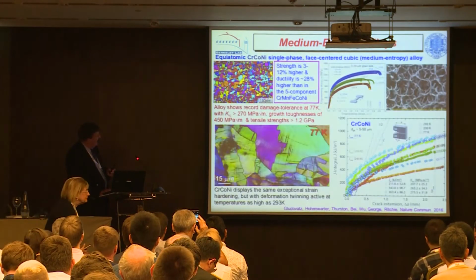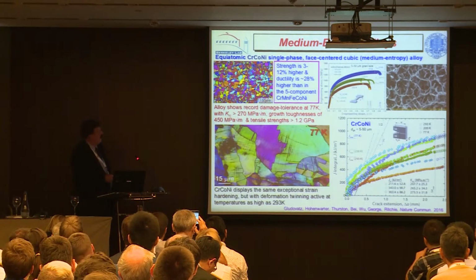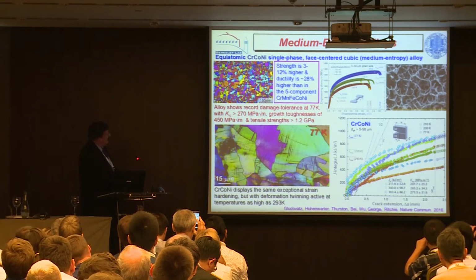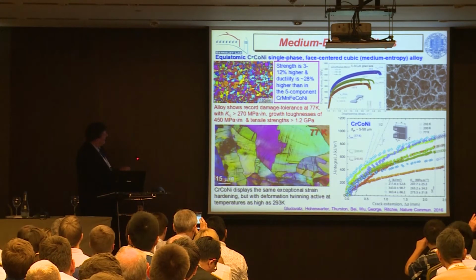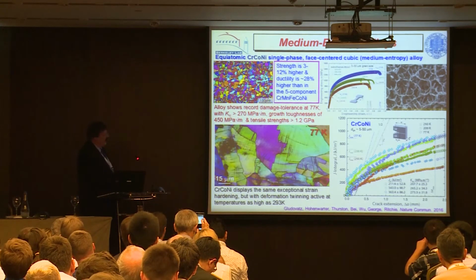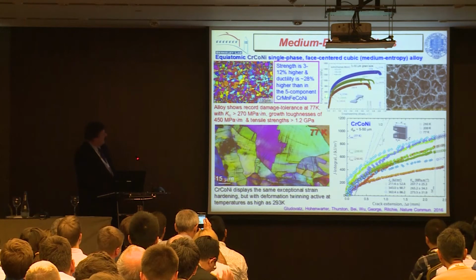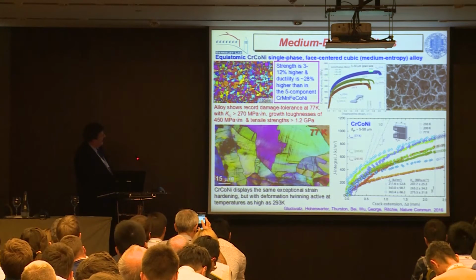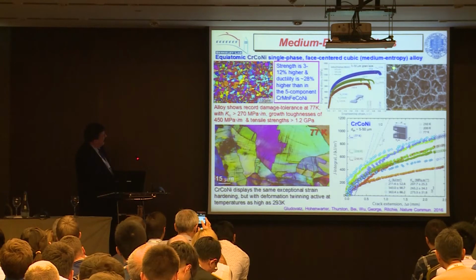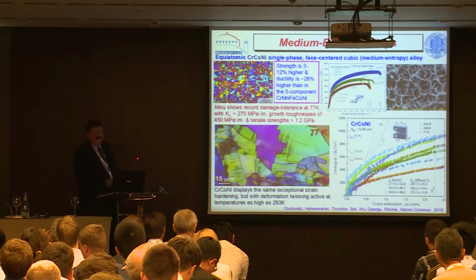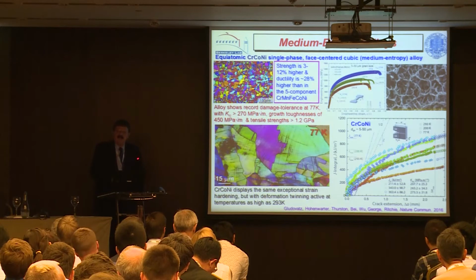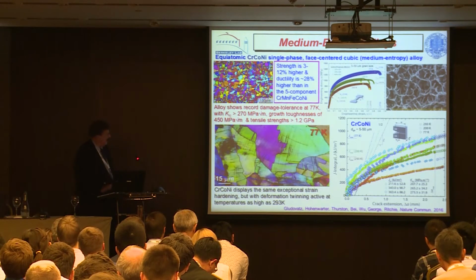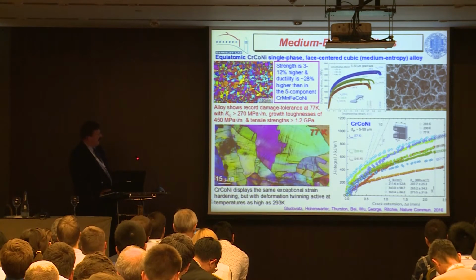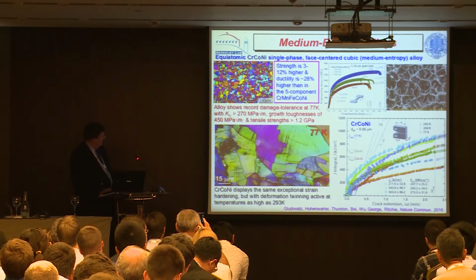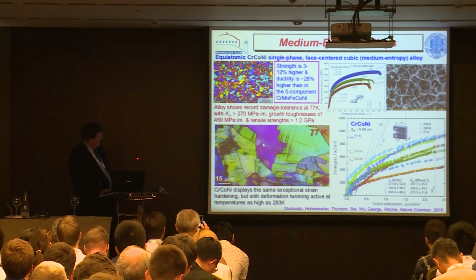Just quickly, we've also taken elements out of these materials. We took two of the elements out to have a cobalt chrome nickel material, and it's even tougher and stronger. Its strength is now up to about 1.4 gigapascals, and it has 90% tensile ductility at liquid nitrogen temperatures. So this material is harder, it twins at room temperature. You can see the twins in a simple microstructure here.